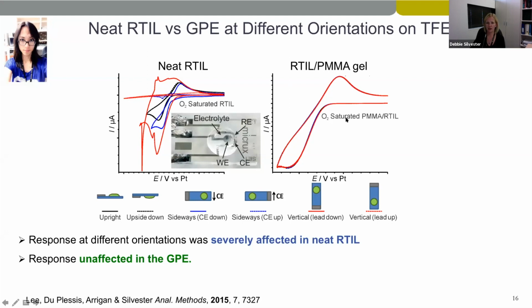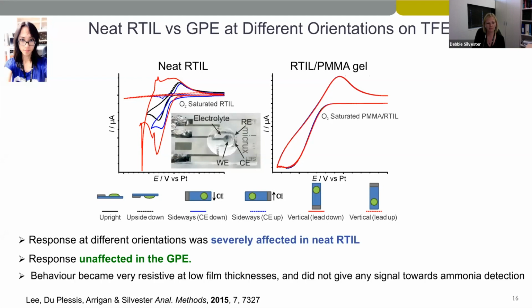Whereas on the right hand side, the ionic liquid polymer gel, so the gel polymer electrolyte, we see identical oxygen reduction responses at all orientations. So this was all really good, but we found that when we tried to go to thinner layers in order to improve the response time, the film became very resistive. And additionally, it also didn't give any signal towards ammonia detection.